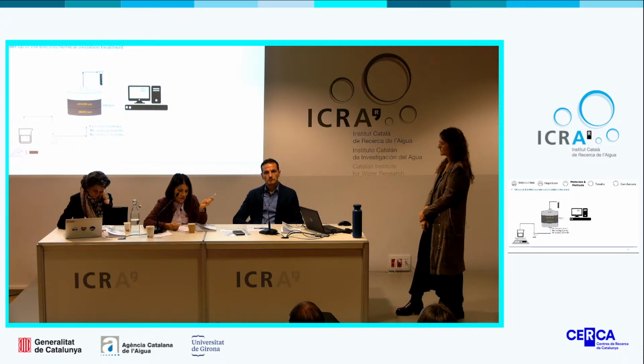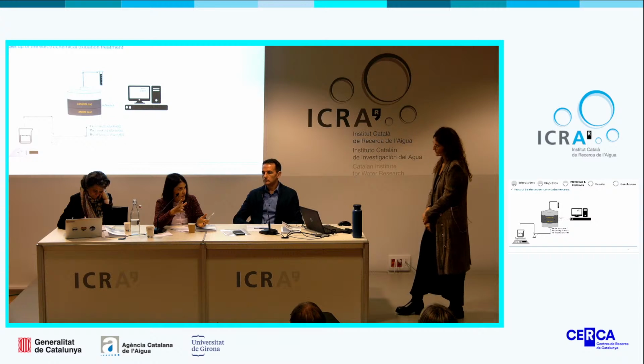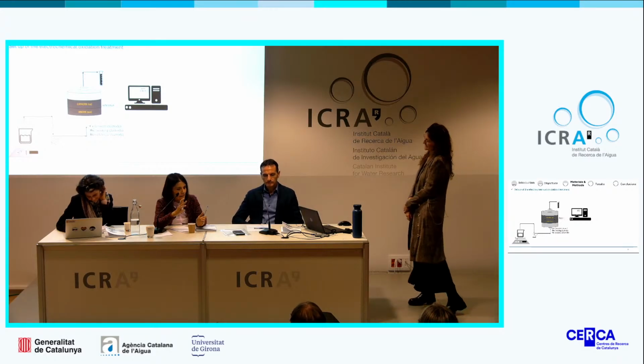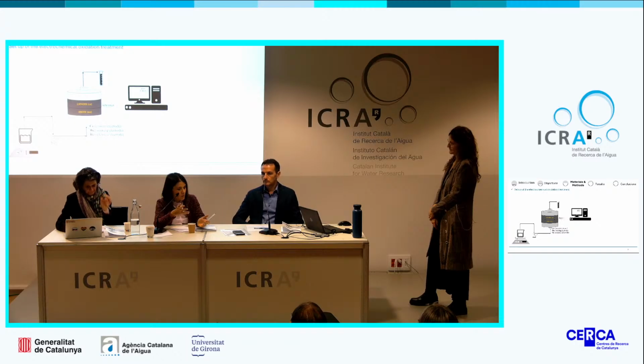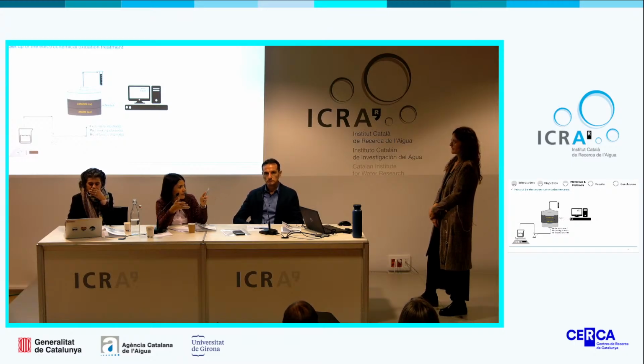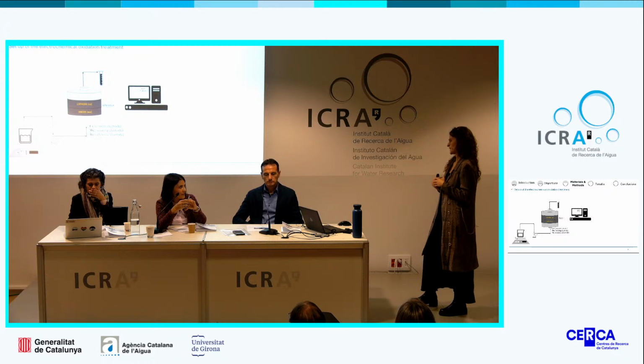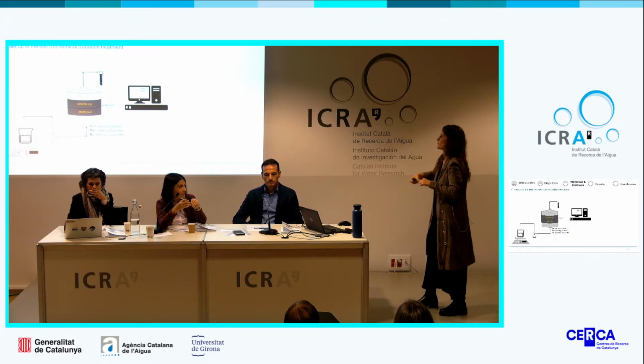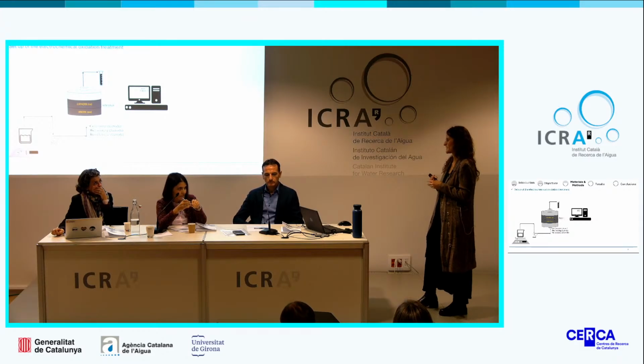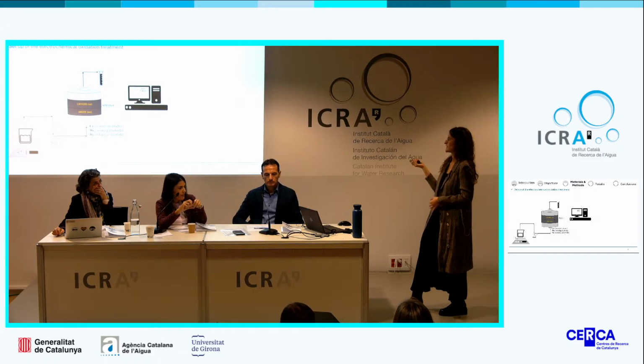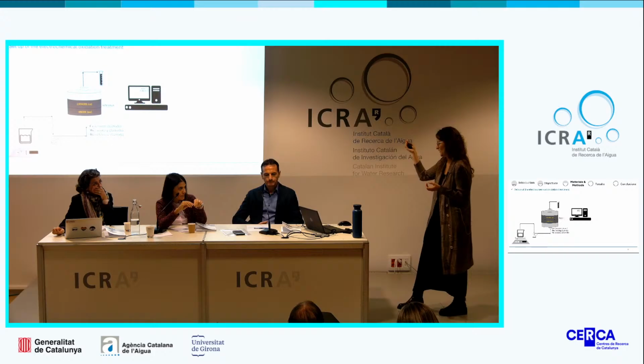Okay. And you mentioned before that electroporation is the main cause of the inactivation of the bacteria? This is my hypothesis. Yes. Your hypothesis, okay. But the mechanism of how ozone or hydrogen peroxide can inactivate the bacteria could be different; they attack the internal part of the bacteria. But electroporation is a phenomenon which occurs through a clear formation of pores in the cell structure, the membrane of the bacteria. Yes, exactly. And through scanning electron microscopy we could see the different pores.